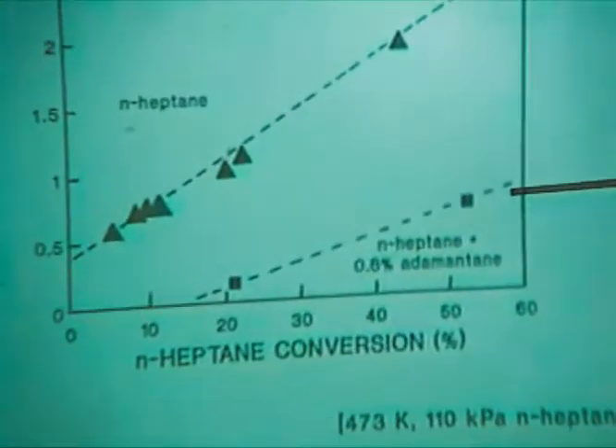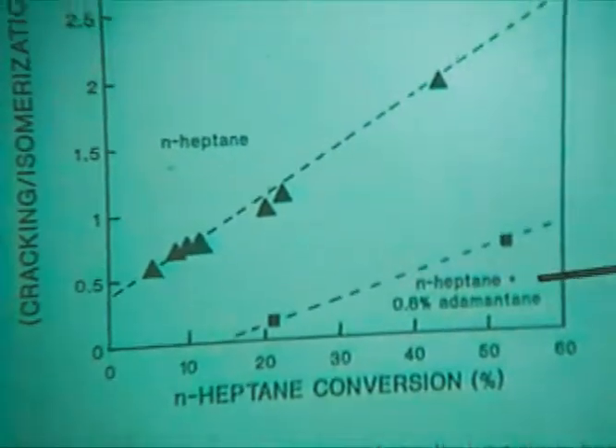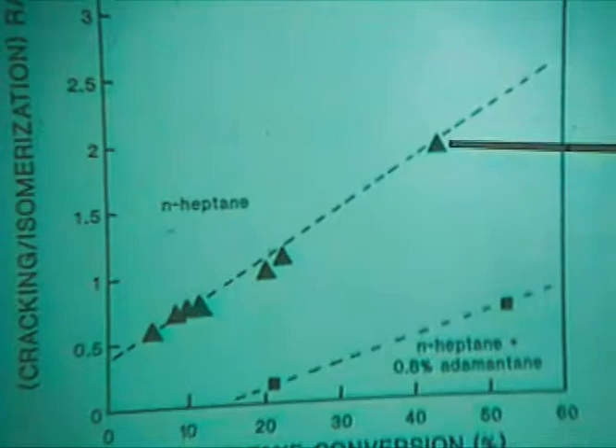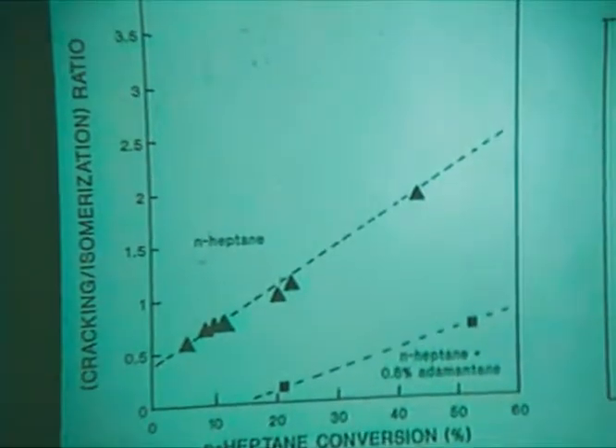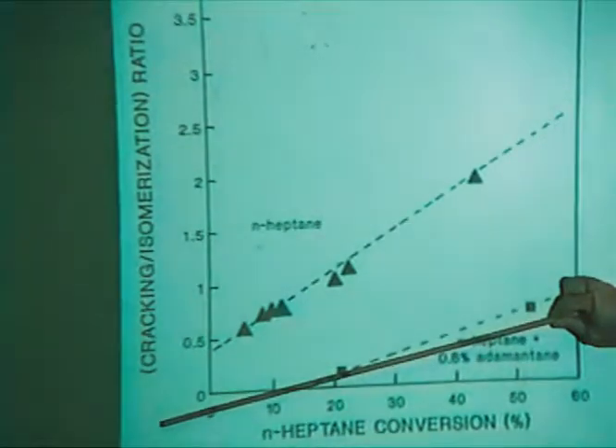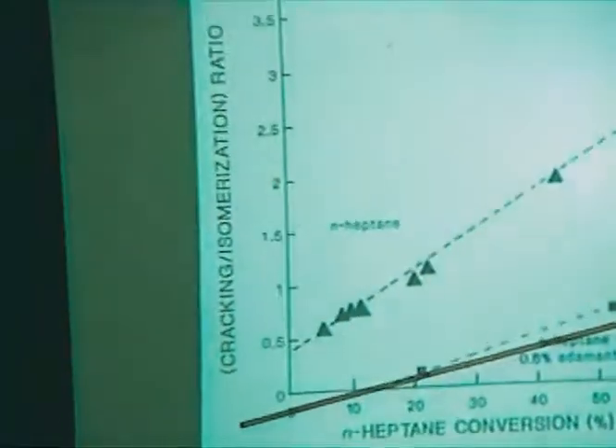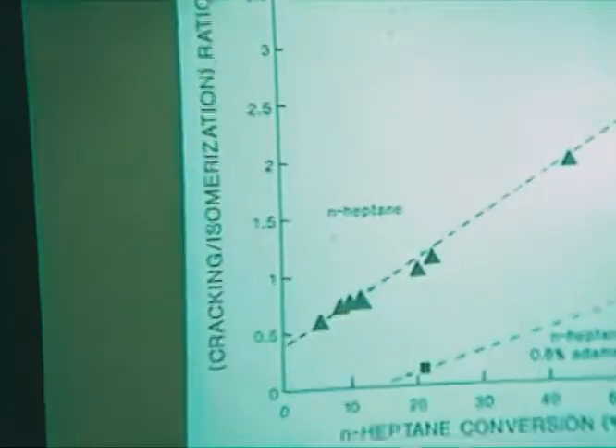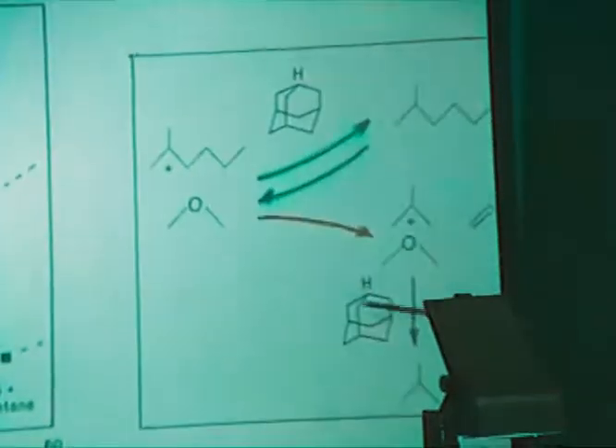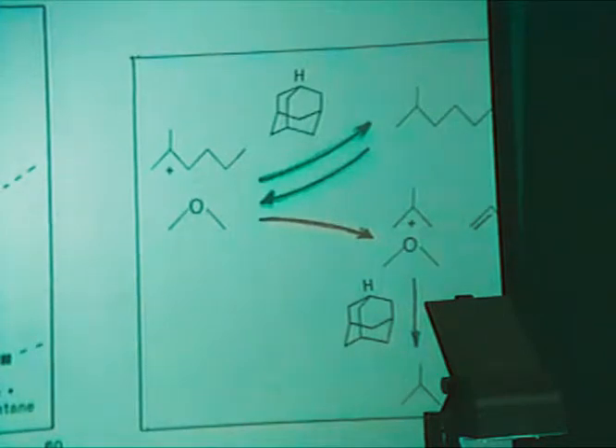And if I look at the turnover rates now as a function of adamantane concentration in the system, what I get is I get an increase in the total rate as I increase the adamantane concentration. The remarkable thing is that this effect occurs when I have one molecule of adamantane for each 200 molecules. So it must be a very good thing that takes you from here to here by a factor of three. What is more remarkable is that it is the isomerization rate that is increasing. In other words, I'm getting these things off of the surface much faster than before, and I have restricted the rate at which I actually crack those carbocations on that surface. So I have accomplished two of my goals. One of them is to increase the rate of turnover by increasing the rate of chain propagation. The other one is to decrease the probability that this will crack by getting it off the surface quickly.